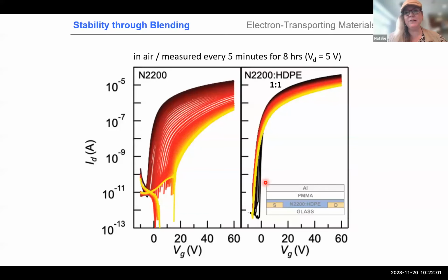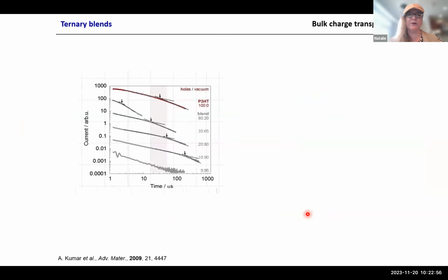What I also like to highlight here, because people always said, well, you have vertical phase separation, the P3HT or N2200 goes to the bottom, the polyethylene on top. Here, contrary to the transistors we did with TPP, TTT, we used a top electrode, so a common top electrode. This means the charges you create are now on the top surface. So when we blend with polyethylene, we get a very symmetric vertical phase separation where the semiconductor goes to both interfaces, which is unusual because the top interface when you make the film is very different to glass. Therefore, we looked at the bulk transport. So really, rather than having charges moving at the interface, really going through our films.